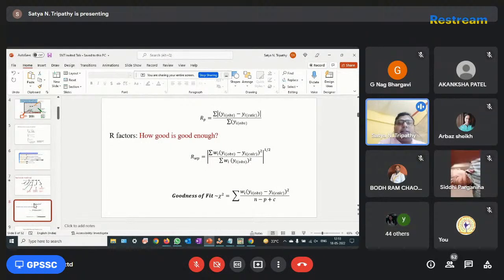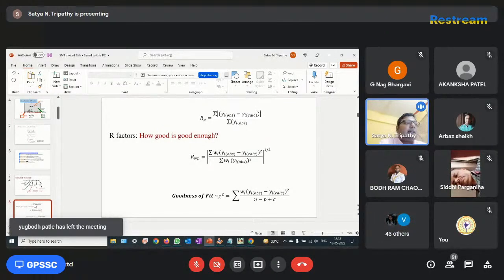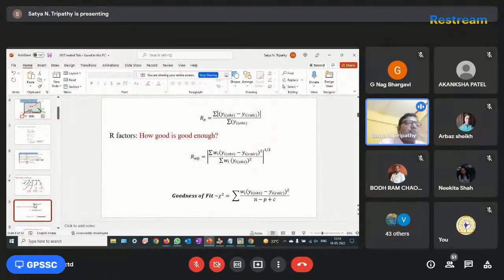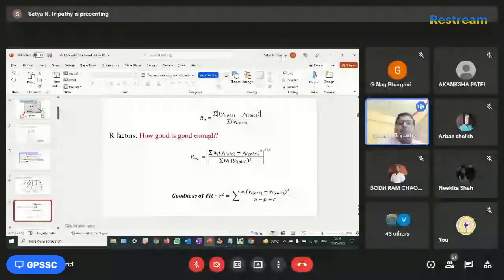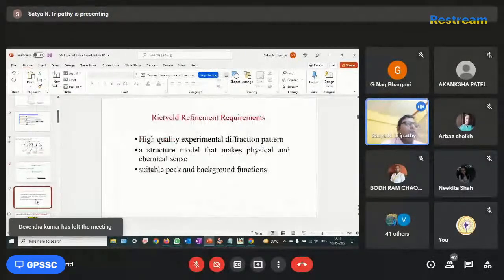So there are various factors, that is Rp and Rwp. These are basically ratios of intensities, and the goodness of fit is also a ratio of intensities. Here N is the number of data points, and P is the number of parameters. These parameters will tell you how good the fit is, that is, how, having the XRD data, we match our calculated intensity to the experimental data. This is our main task. The details of the theory you can find in Young's book and Rietveld's book. You can go there and see, but I will show you how to do this method.